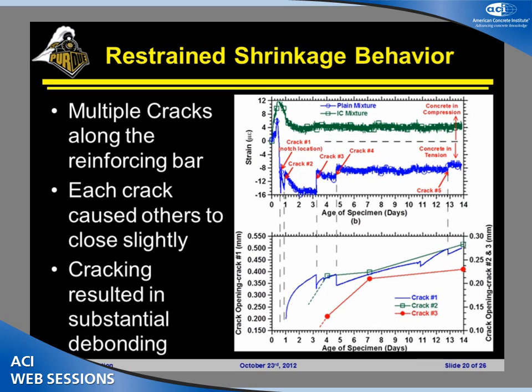What's really interesting about this is we set this up so that we can actually monitor the cracks that are developing, monitoring the width of the cracks. Here you see the first crack that's developing. As the second crack starts to form, we see the crack gets a little bit narrower and then starts to pick up again. The next crack forms. We can see this repeated pattern. The second and third cracks we're not monitoring with the continual monitoring that we're using here, but we're just monitoring the widths that are forming. So we get a fairly stable size of the cracks that are forming in the system.